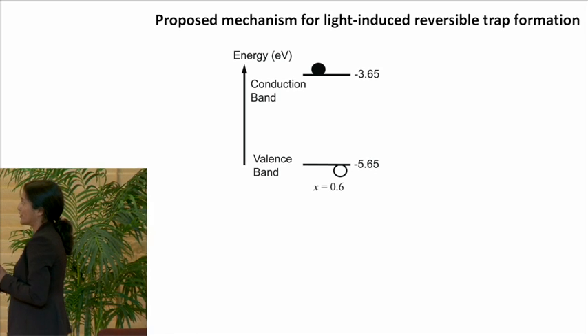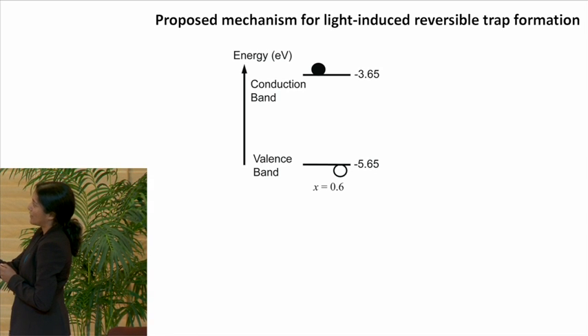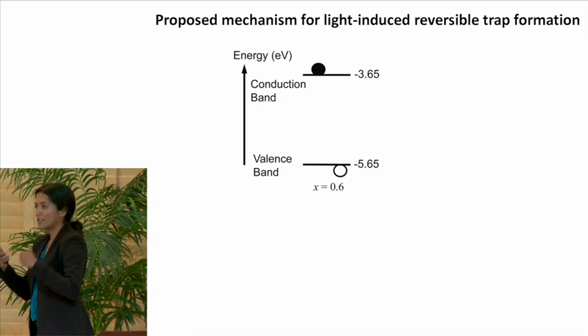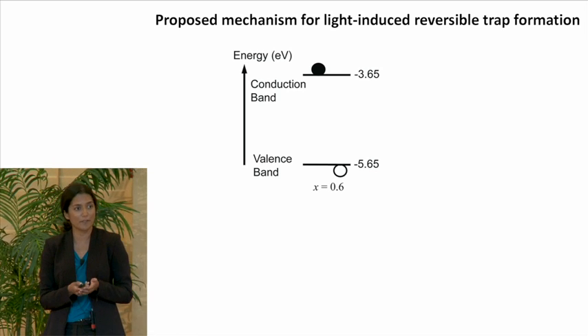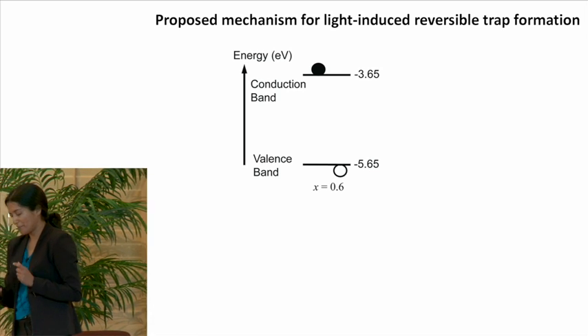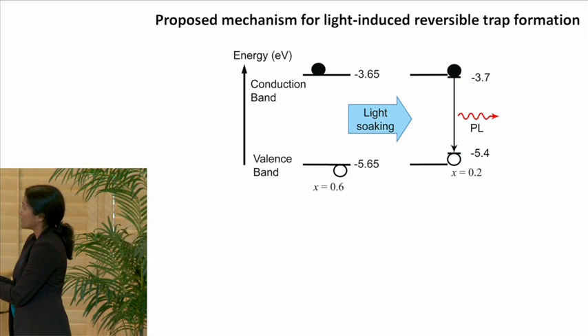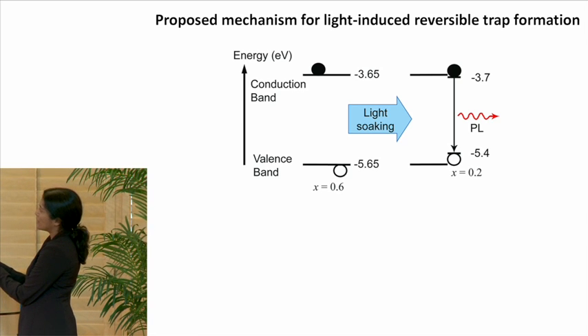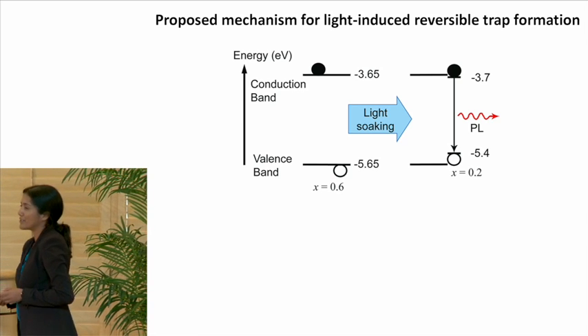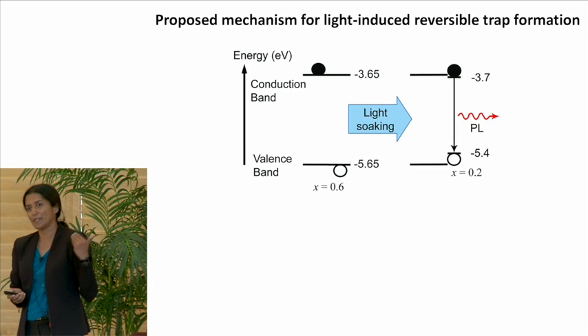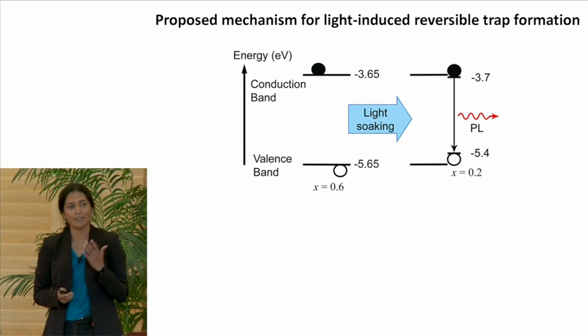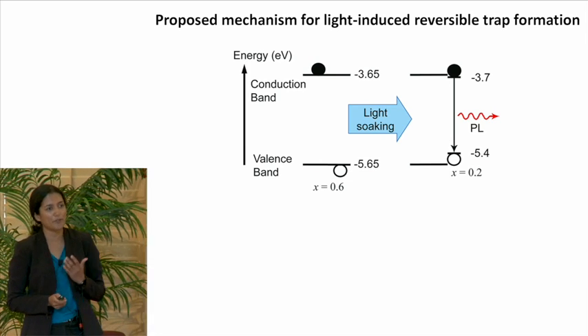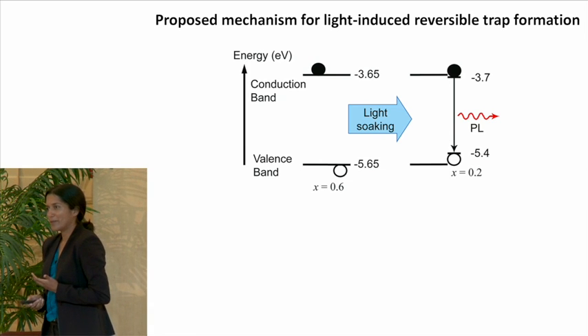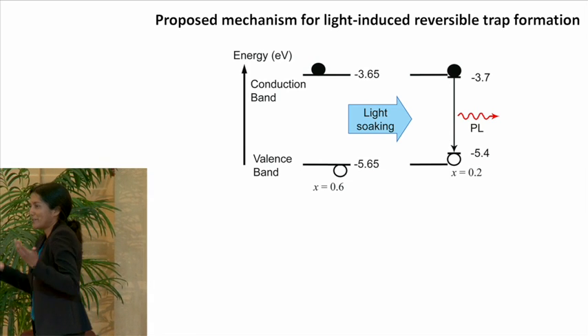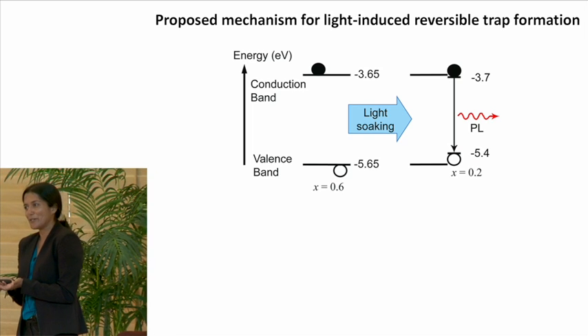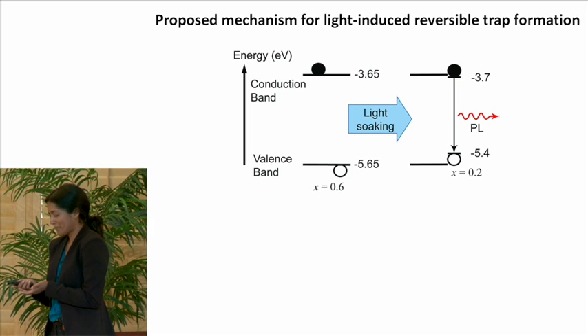initially, the photoluminescence comes from these electrons falling from here to here. But in time, we get this low energy photoluminescence band, which means we're forming a trap. So here's my trap. We have some state where the holes fall into a state with lower energy. We know that the energy of this photoluminescence corresponds to the same energy as the photoluminescence from an x equals 0.2 material. So we ask the question, maybe why not form the x equals 0.2 material, but only under illumination?